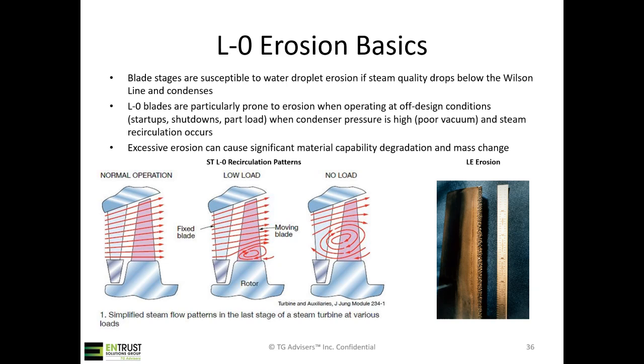If you've got poor vacuum during those off design conditions, you can actually get steam recirculation. As shown in that image at the bottom there, during low load and in particular no load, you can actually get the steam flow start to recirculate. The most common place for erosion is going to be the leading edge of your blade, especially towards the tip, maybe like the top third of the airfoil. But if you spend a lot of time at low or no load, you could have erosion on the trailing edge of your blade. That's usually down more towards the blade root. That trailing edge erosion is more concerning, since you've got higher stresses in that area, there's more material outboard of it pulling on that area, basically.